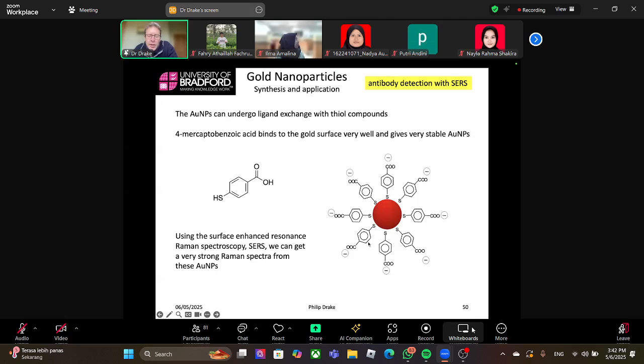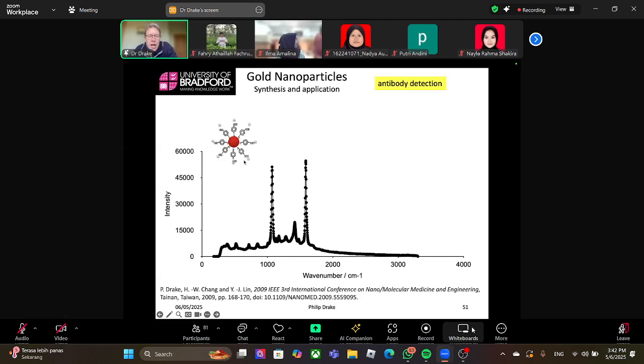This has a very strong Raman signal, and because of the nanoparticle, you get a very strong surface enhanced resonance Raman. So when your Raman laser matches the SPR of the gold particles, you get enhancement and you get very strong signals. These 2 peaks are characteristic of the protons on the benzene ring. The carboxylate surface is the peak in the middle.